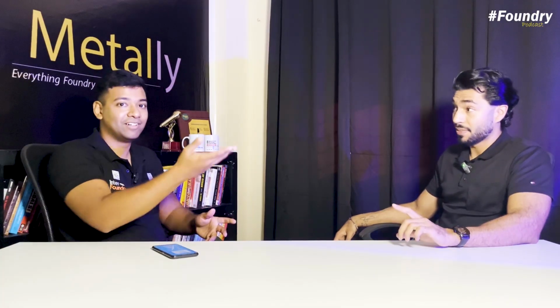So I'll take a specific case of chain sprockets. These chain sprockets are massively getting manufactured through the ADI process. There you have an application already. These sprockets are machined after austempering. So they account for the volume expansion of 0.2%, which happens in the austempering process as well. But these grade 1, grade 2 products, you can machine after austempering.